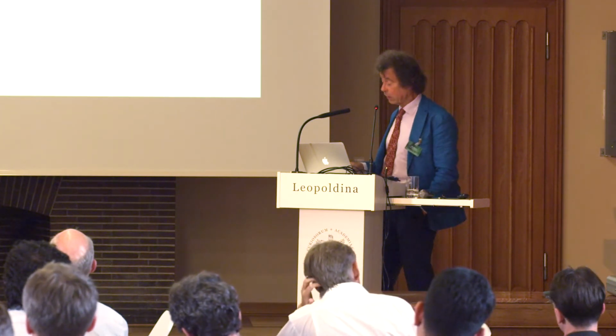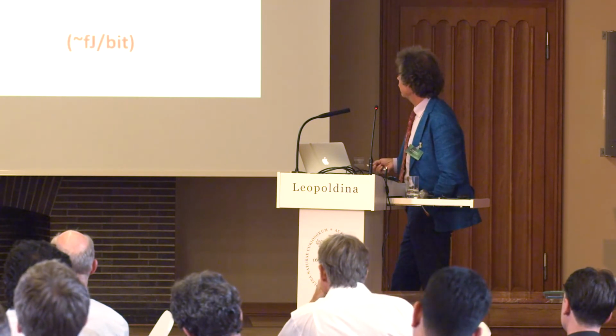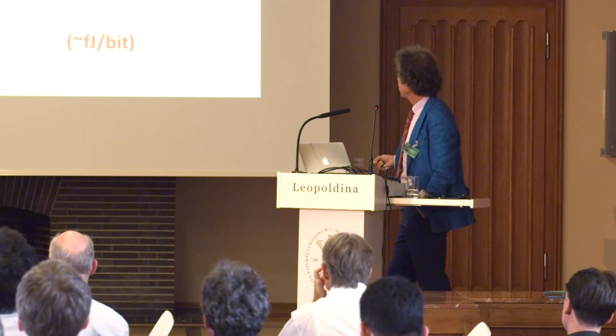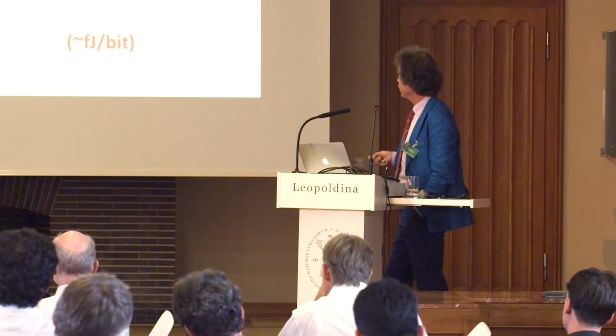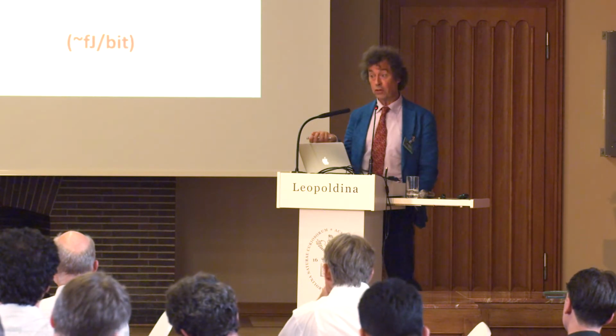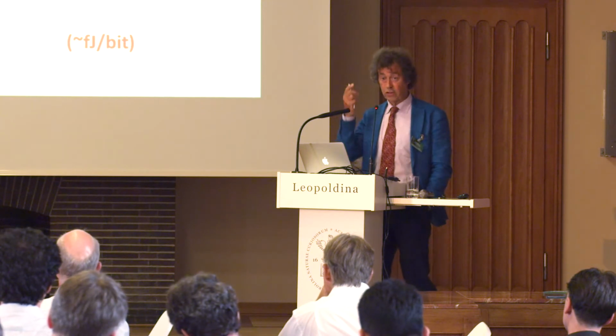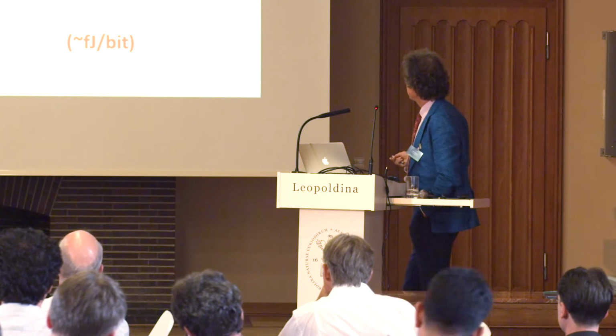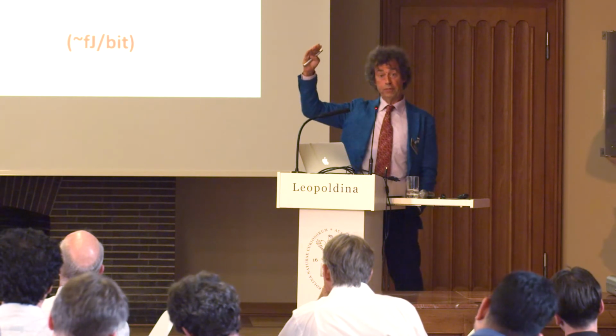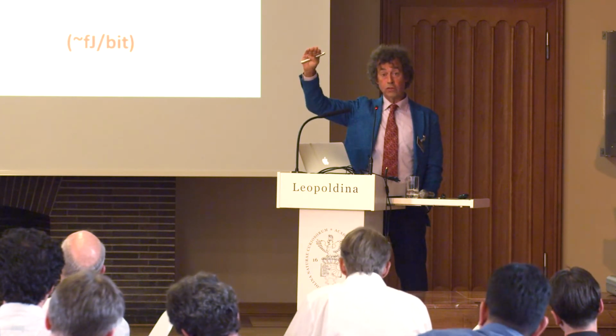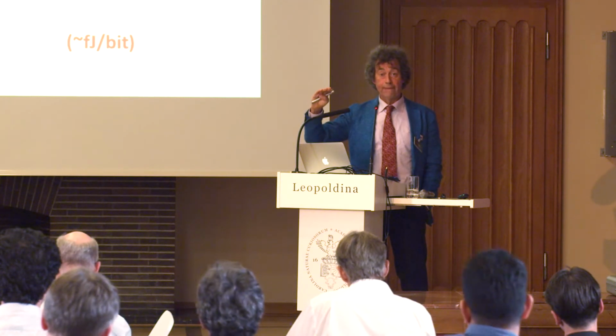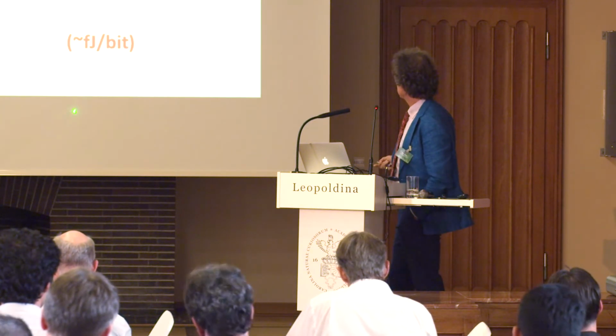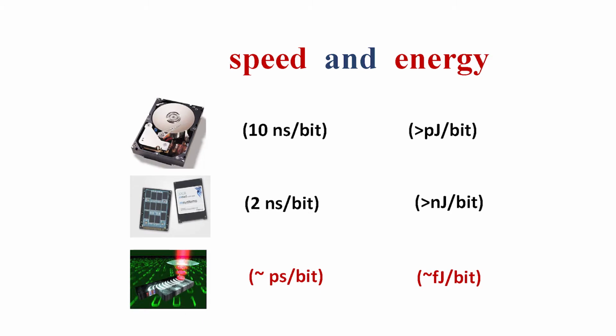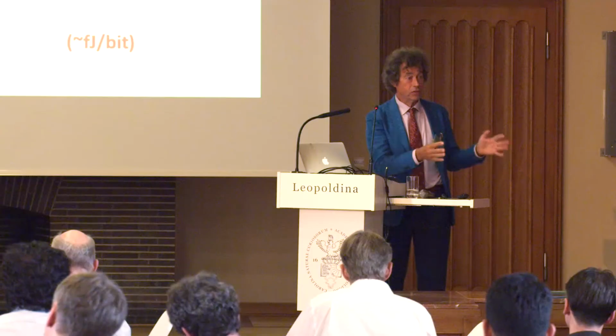And now if we look at our way of optical storage, we can not only do this very fast, not on the femtosecond, but effectively on the picosecond time scale, which is already 3 orders of magnitude faster. But the energy per bit we have now brought down from the nanojoules to the femtojoules. And that was a few years ago when I started to think, wow, so it is possible. Of course, doing this for one single bit doesn't make it into a device yet.